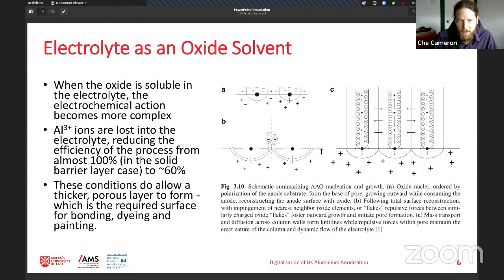The interesting thing about most aluminium anodization processes is the electrolyte that the aluminium is in when this anodization is being performed actually dissolves the oxide layer as it's forming at the same time. So this has a couple of effects. One of the things it does is reduce the efficiency, but what you do get is this very interesting porous layer going on top of a solid layer, and it has a lot of different properties, and this is what we're interested in most of the time.